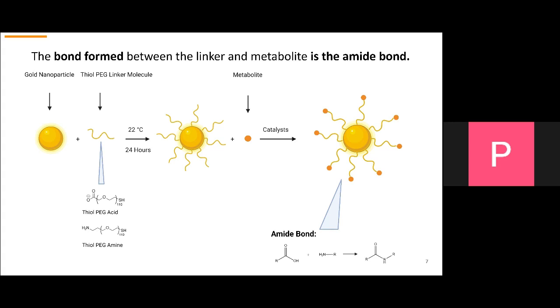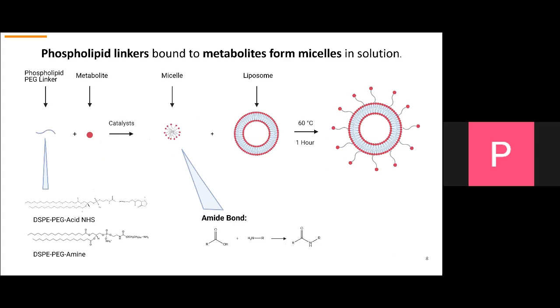When the linker has a carboxylic acid present, it's also necessary that the metabolite has a primary amine, and vice versa for binding. As for liposomes, we use a phospholipid PEG linker, where the phospholipid PEG linker is compatible with the membrane of the liposome. First we bind the metabolite to the linker, and they form micelles in solution. Then these micelles are incubated with liposomes at 60 degrees Celsius to raise the phase transition point so that we're able to anchor these linkers and metabolites into the surface of the liposome.